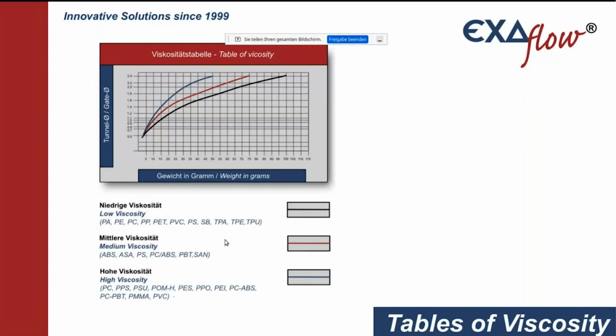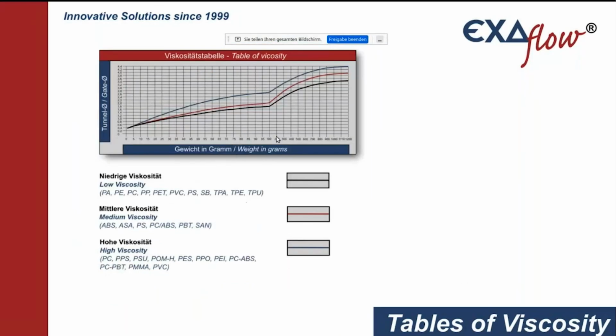So let's say we have a medium viscosity plastic part in ASA, and the weight is 35 gram. So you look here, 35 to the red line. So the gate is maybe 1.7, 1.88 millimeters. For larger parts or heavier parts, there is also a table of viscosity we see here. So this is for you, from us, to have an idea how to inject with which gate diameter.